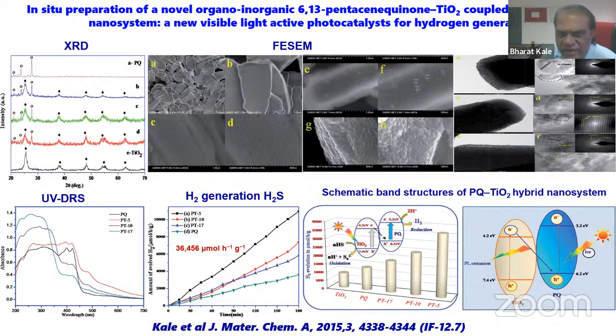pentacene quinone. Pentacene quinone is a layer structure. You can see all kinds of layers. If you see the FESEM, these are the layers. In these layers, if you have coupled TiO2 nanoparticles sandwiched in between the two, then it helps a lot for suppression of the electron-hole recombination, and that really helped a lot. We got